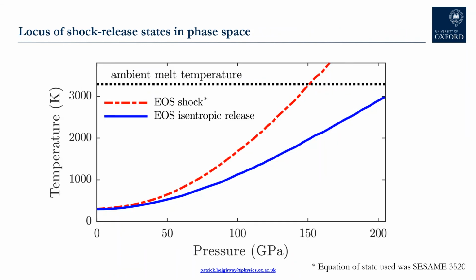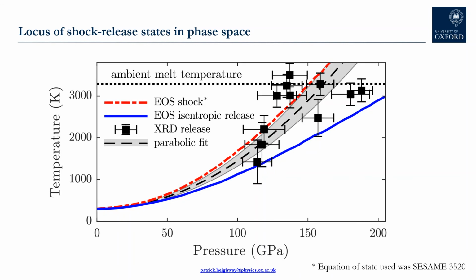So in this last figure, I'm showing in the pressure temperature plane the Hugoniot, i.e. the locus of shock states, and the locus of corresponding isentropic release states as a function of shock pressure. I'm also showing where the ambient melt temperature of tantalum falls, which is about 3300 Kelvin, for reasons we'll come to in just a second. I now show the release temperature we infer from thermal expansion as a function of shock pressure, along with a simple parabolic fit and its 95% confidence interval.